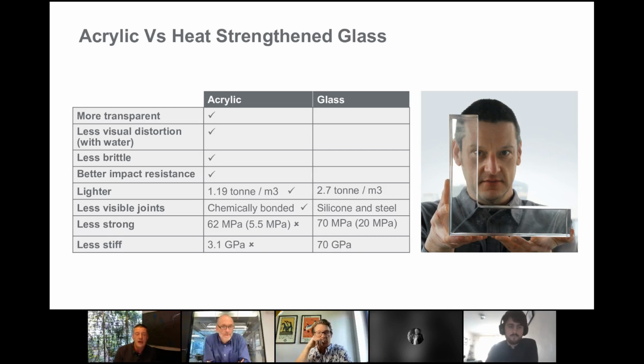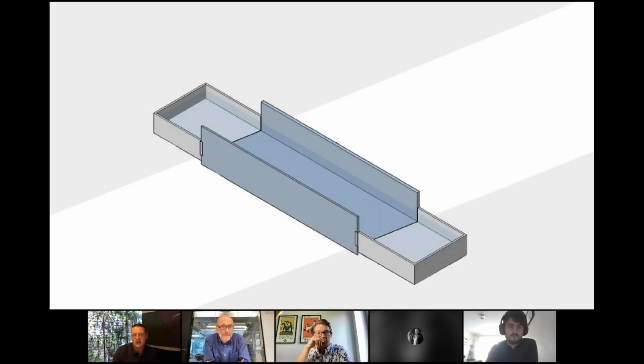increase in deflection. However, it so happened that in this structure that we just looked at, we need this wall on the side to stop people falling out of the water. So we have a beam 3 meters tall, effectively, and it turns out that a beam 3 meters tall, approximately 200 millimeters thick, made of acrylic, is just about what you need to span 15 meters across this gap. So that's it in principle.